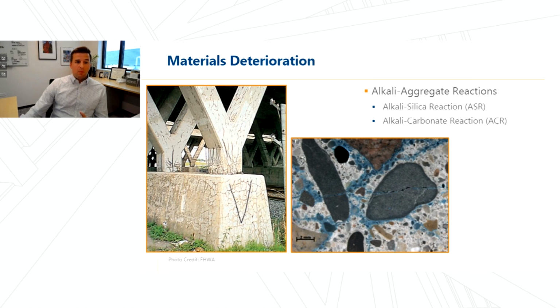And so when it comes to new structures, the regions where we have reactive aggregates are pretty well understood, and there's ways to mitigate that in the mix design for a new structure or by managing the moisture and surface. But if we have an existing structure, and it may not have necessarily been a known concern at the time of design, we're unable to reverse the damage. We might be able to slow it down by controlling moisture, but if it's heavily advanced deterioration, if it's deleterious, we may be in a situation where we're forced into full replacement.